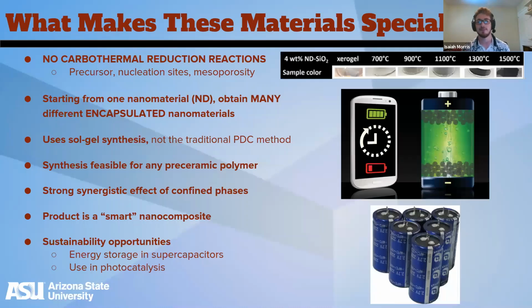Now, what makes these materials special? Well, for starters, the main thing is that they exhibit no carbothermal reduction reactions, which, looking at the chemistry and the material itself, there should be some. So obviously, the nanodiamond has to be having some sort of effect, and it is. For instance, when we talk about nucleation sites, I spoke earlier about how nanodiamonds have a very large surface area to volume ratio. Well, all that does is provide many, many nucleation sites for silica to crystallize on top of the surface of this nanodiamond.